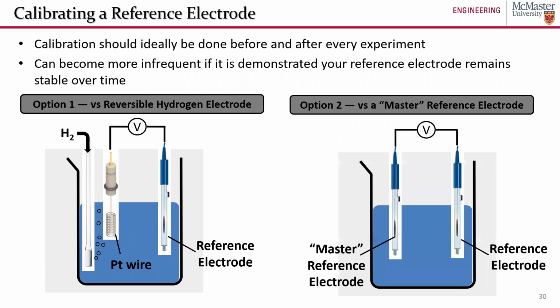Another way to do it is to have what one might call a master reference electrode. So it's a commercial reference electrode that you store away in its proper storage solution. You give it all the tender love and care. You take good care of it. You protect it with your life, so that you know that this thing has been treated very well, and it's going to be very stable. It's not going to drift over time. And you can always measure your other reference electrodes, the ones you're beating up on a daily basis, using all the time. You can measure the potential of the 2 versus each other to calibrate the reference electrode you use all the time to this master reference electrode that in principle should not have drifted from its default value.